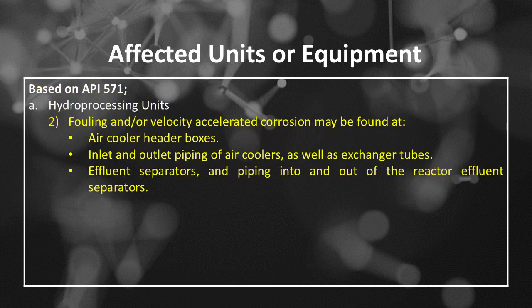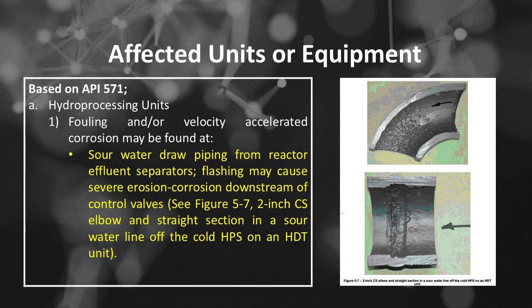Number 2. Fouling and/or velocity-accelerated corrosion may be found at air cooler header boxes, inlet and outlet piping of air coolers, as well as exchanger tubes, effluent separators, and piping into and out of the reactor effluent separators. Sour water draw piping from reactor effluent separators. Flashing may cause severe erosion corrosion downstream of control valves. See Figure 5.7, 2-inch CS elbow and straight section in a sour water line off the cold HPS on an HDT unit.